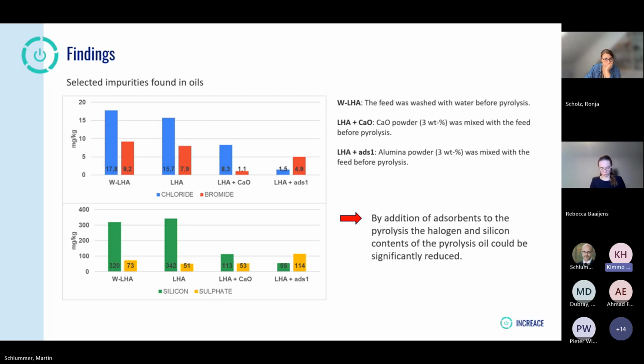And you can see that both calcium oxide and alumina caused a quite significant decrease in the chlorine, bromide, and silicon contents in the oil. Of course, not going close to zero, and not close to the level which is acceptable for the steam cracker, but anyway in the direction that the next step would then be upgrading, meaning some kind of hydrotreatment. So it's already better than those very high concentrations. Sulfate here, maybe with this alumina, it may contain and leach some sulfur. We also saw that some trace metal contents increased. So that was what I was going to present, and then somebody else continues from this.